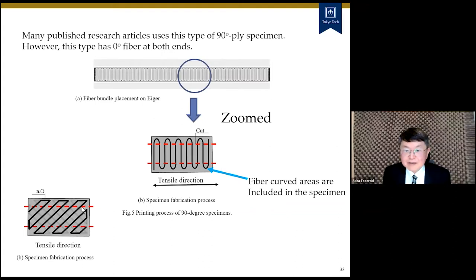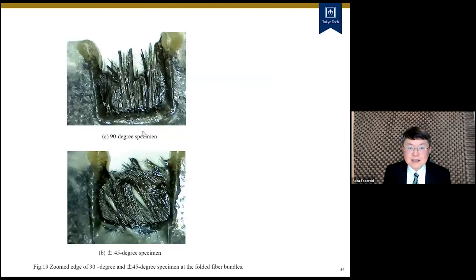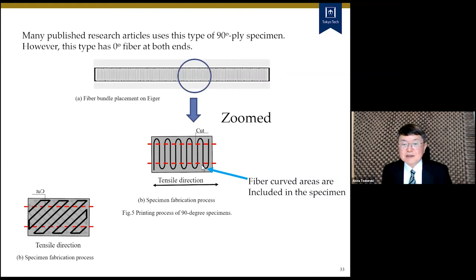In these curved areas, this is a 95 degrees specimen, so just a little bit different from the 90 degree. So we used a gas burner to burn the resin, and we found the fiber breakage here. So the specimen that includes this has largely affected the fiber curved area. So the published research articles that include these curved areas are not reliable. We cut this area.